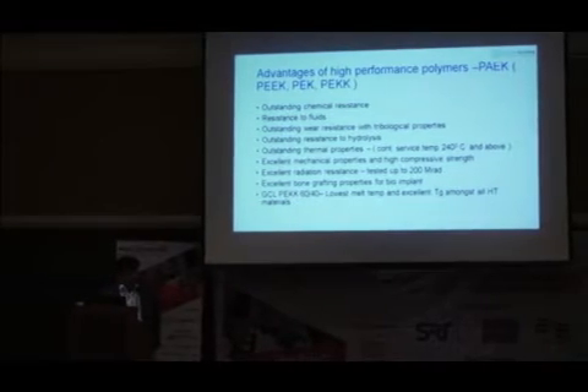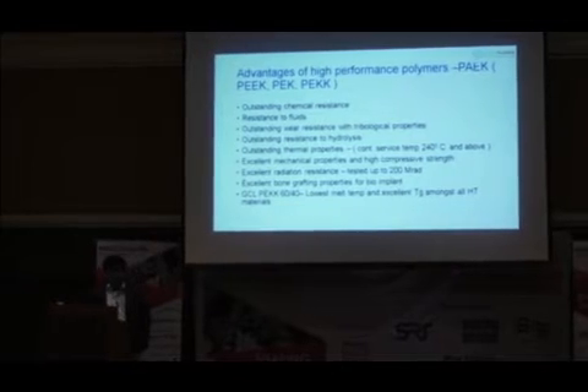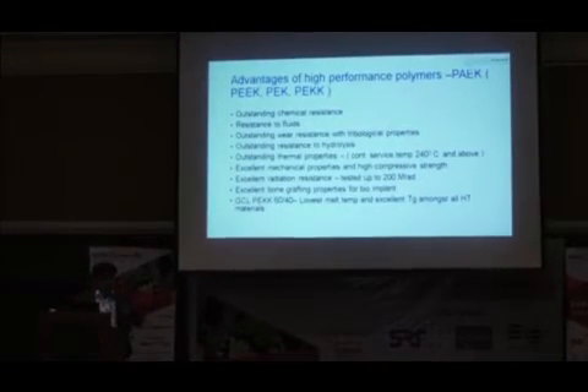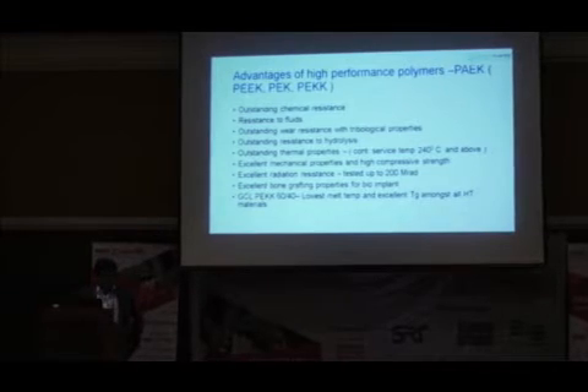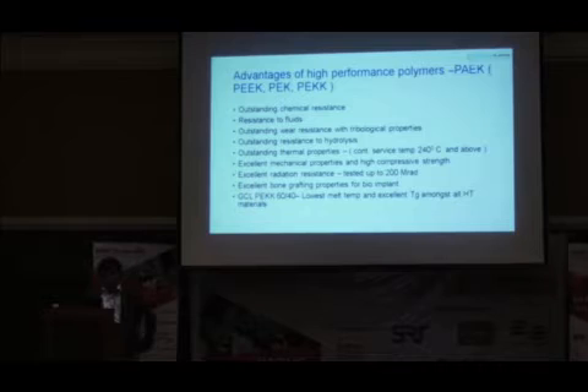Advantages of high performance polymers, what are the special advantages? So it has outstanding chemical resistance, resistance to fluids and aggressive oils and gases, excellent wear and friction properties, and you can see very good tribological properties. The PV values are very good with all these materials, and the hydrolytic resistance is very good, outstanding thermal properties. So continuous service temperature, as I discussed, 240 degrees C to 300 degrees C you can achieve with this polymer. Excellent mechanical properties with good compressive strength. So for biomedical people, this is the most important property. And even in many other applications of textiles and gears, all these properties are considered very well.